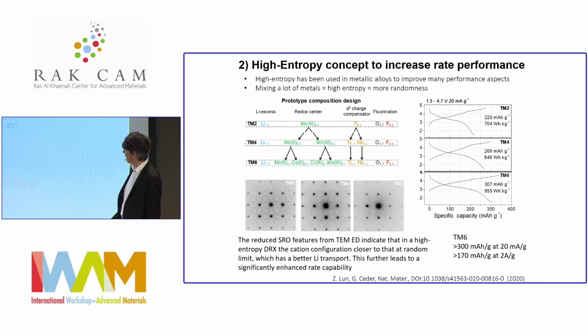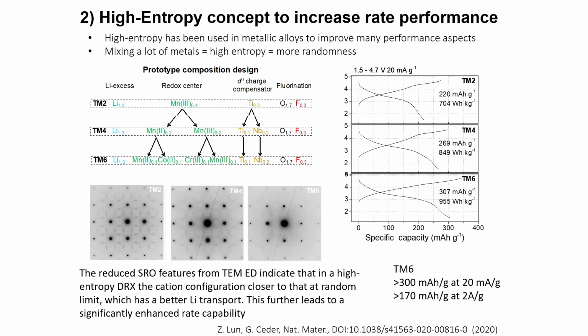Now I go to 6 elements. I split the manganese 2 into manganese and chromium, cobalt. I split the manganese 3 into chromium and manganese, and these are split. So I have 6 elements. I have no sign whatever of short-range order. It's a completely random alloy now, and now I have by far the best performance. I have 955 watt-hours per kg, simply by destroying the short-range order by a high entropy effect.